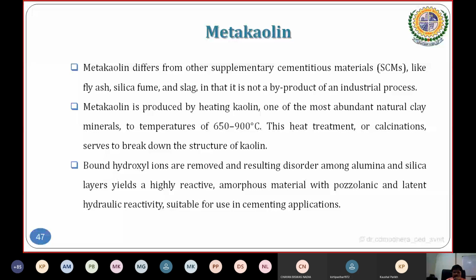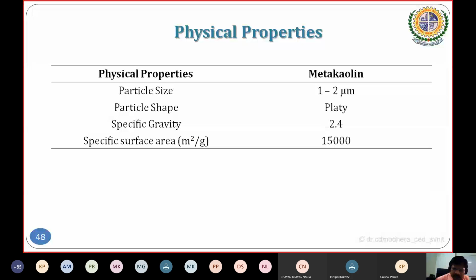Now, if we look at its size or physical properties, the size is more or less 1 to 2 micrometer or micron. The particle shape is platy. Specific gravity is lower, only 2.4. And specific surface area here is different. It is around 15,000 meters squared per gram.